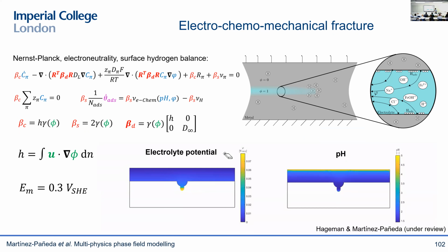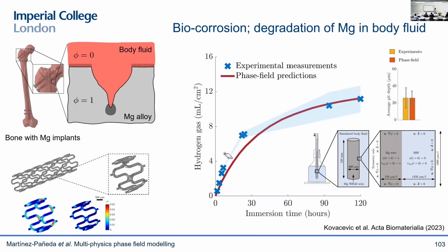And I think last but not least, we have also extended all of this to fracture and combined it with everything that I presented before. So here we are interested not only in modeling the propagation of cracks, but also in seeing how the electrolyte changes within the crack. And this poses some challenges in the context of phase field models, because we don't have a discrete crack, but the geometry of the crack is important for this kind of ionic transport process. So we need to resolve that, and we have proposed new ideas on how to infer a crack opening from these phase field methods. And I think, one last slide.